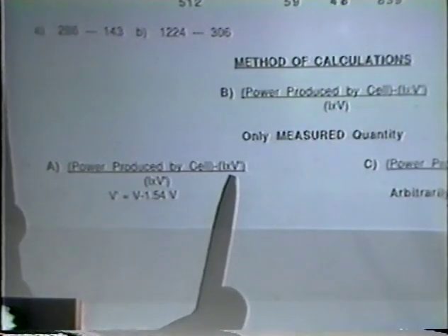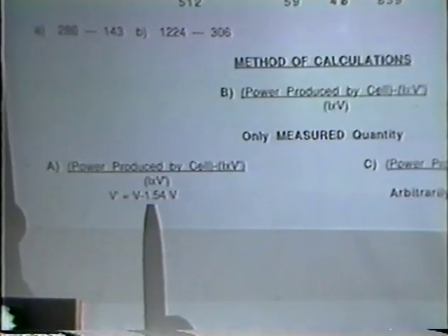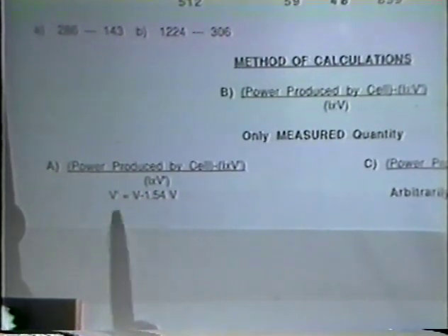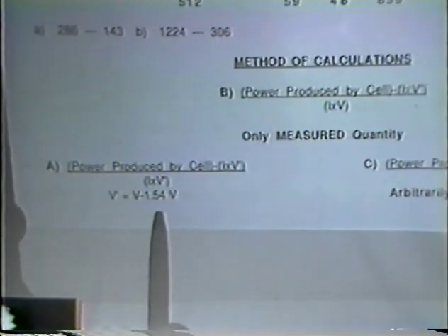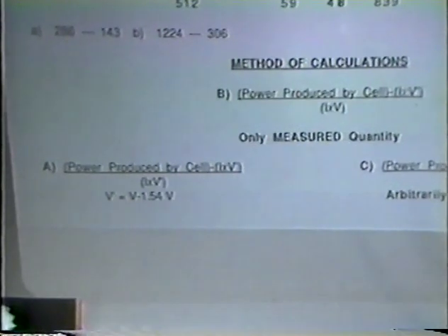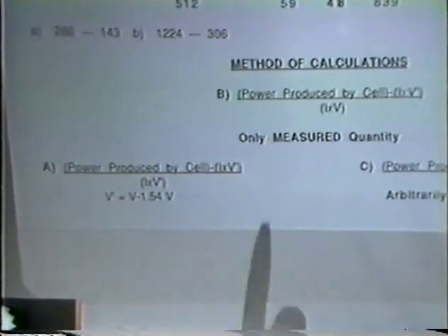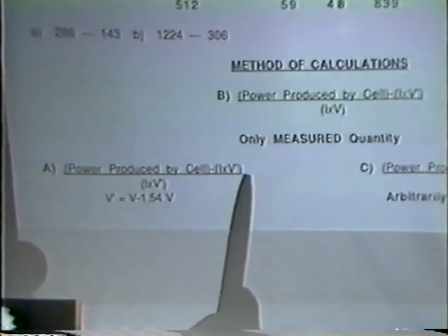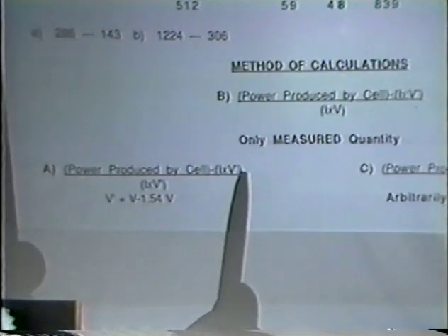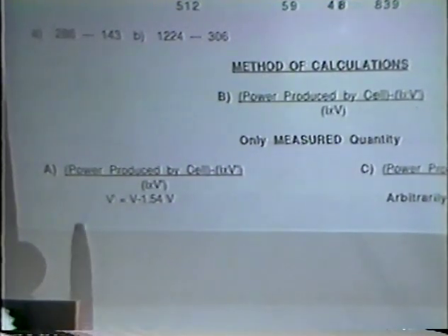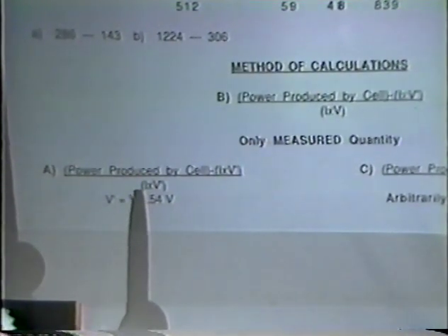It's corrected by the 1.54 volt correction for water electrolysis in D2O. Note it's somewhat different in H2O. It's only 1.48. You have to take that into account in comparing differential measurements in D2O and H2O. And then this numerator, the excess over what you thought you should have if all the gases escaped, is divided by 3 separate quantities to get this column. The first quantity is the amount that you thought you deposited in terms of joule heating. And that's the numerator and denominator here.